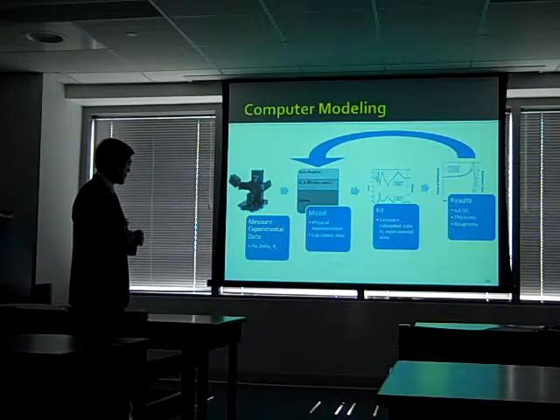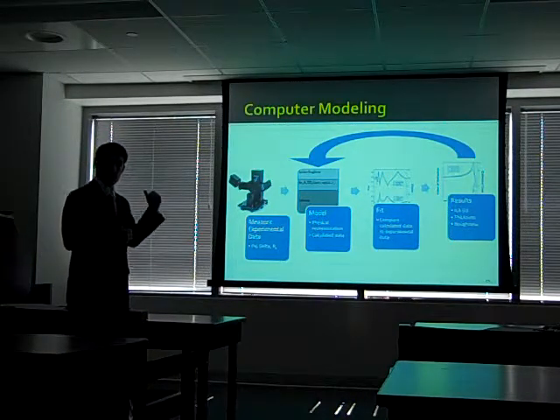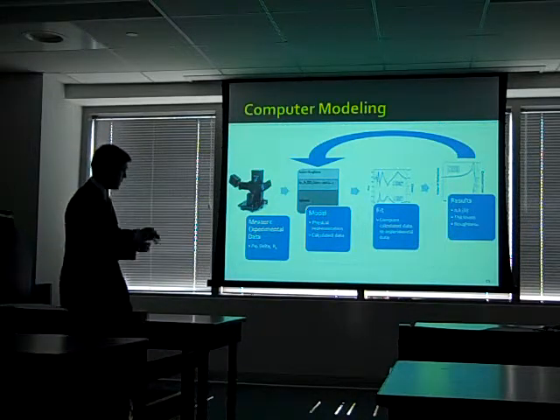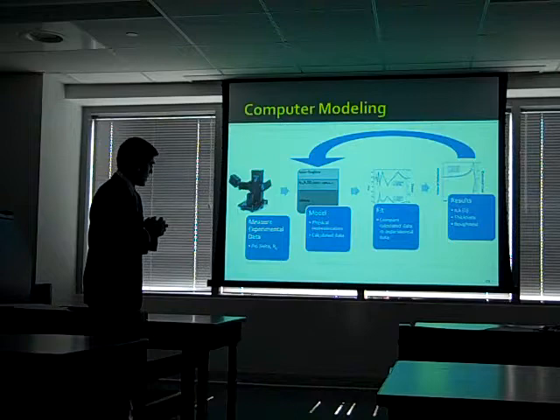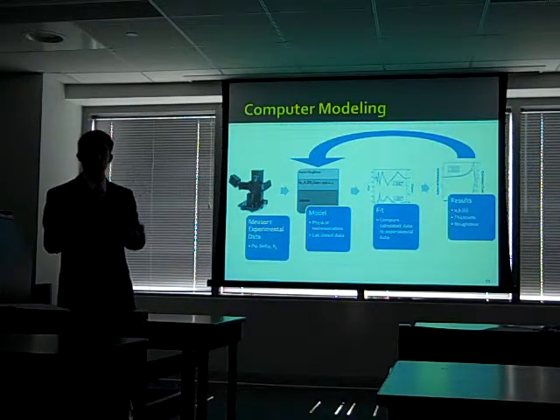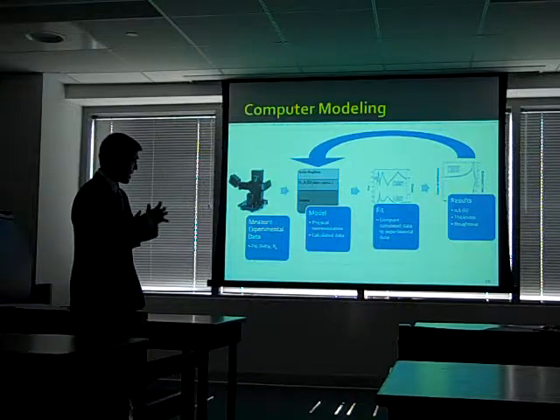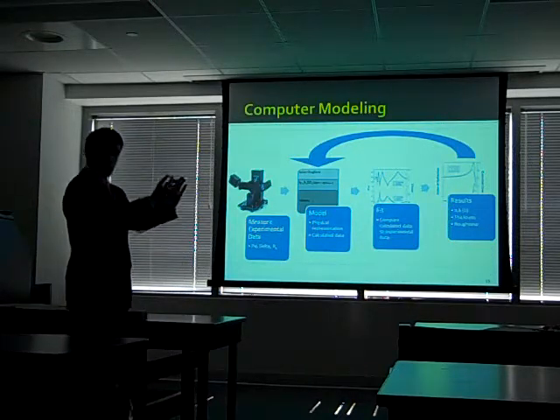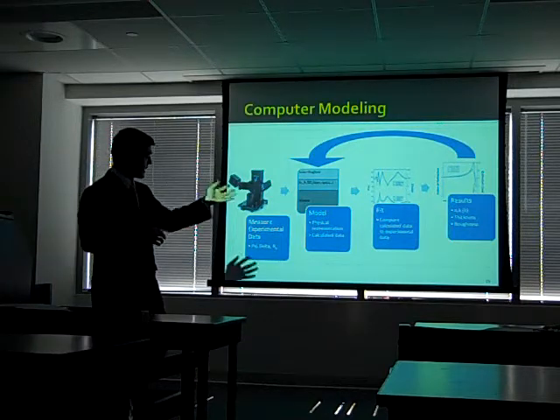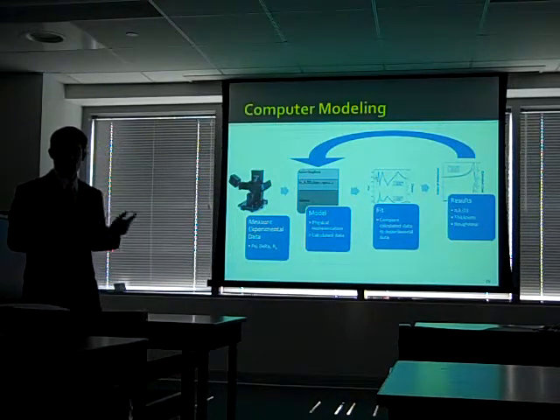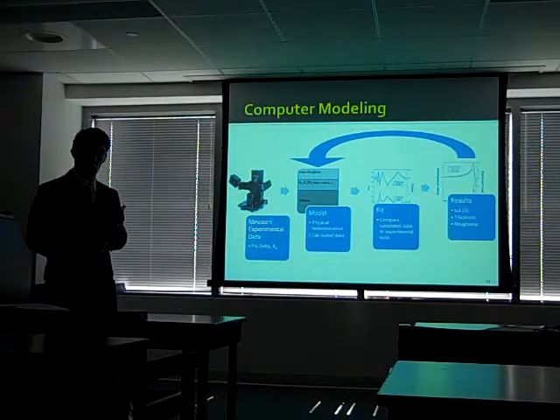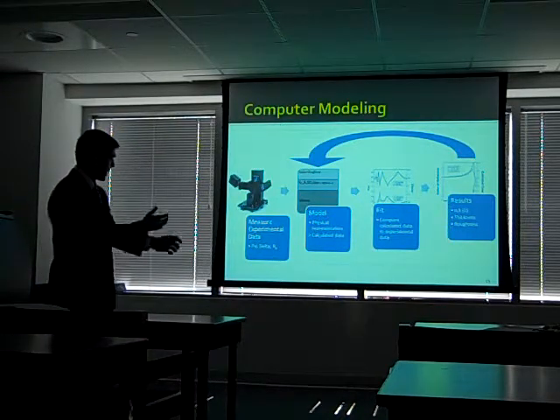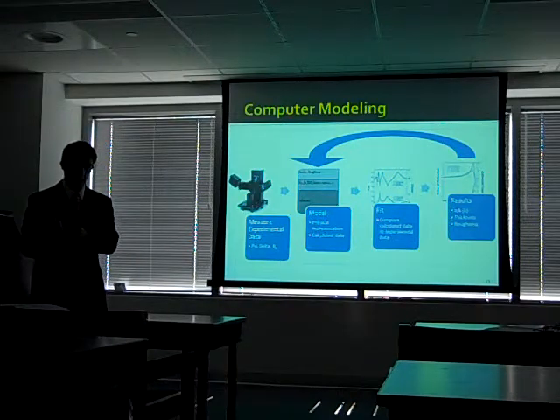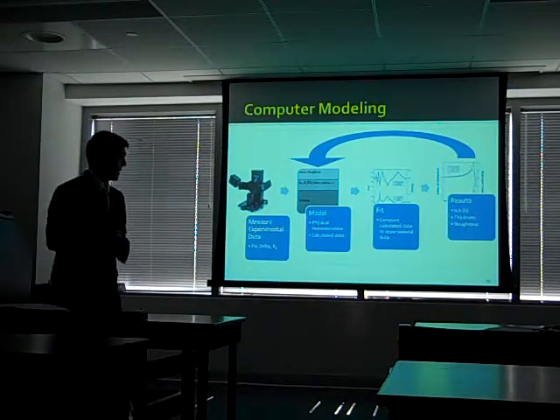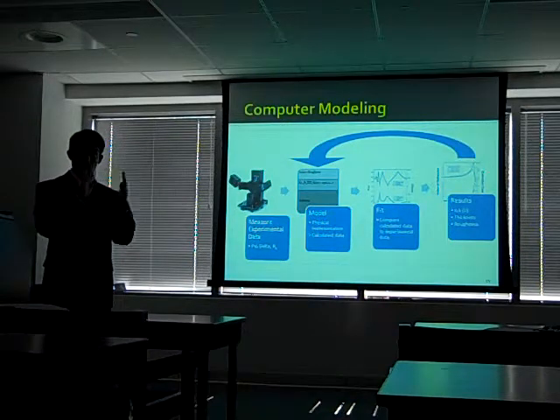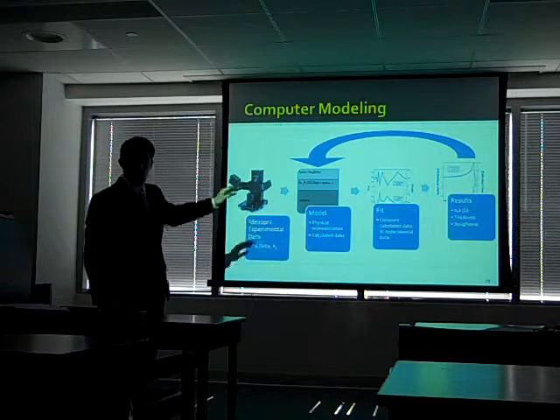This is just a schematic of the modeling process. Modeling starts off with measurement of psi and delta with the ellipsometer. Then we construct that model in the computer program and give it initial guesses for the thickness and optical constants of the different layers. The model then calculates psi and delta based on what you've given it, and the fitting process goes by the use of a mean squared error reducing function. This program uses the global Levenberg-Marquardt algorithm, and the fitting works by comparing the experimentally determined psi and delta to the calculated psi and delta, and the function basically minimizes the difference between the two by changing whichever free parameters you've set in the model.